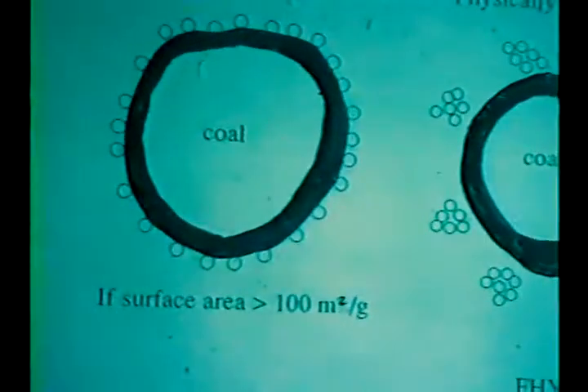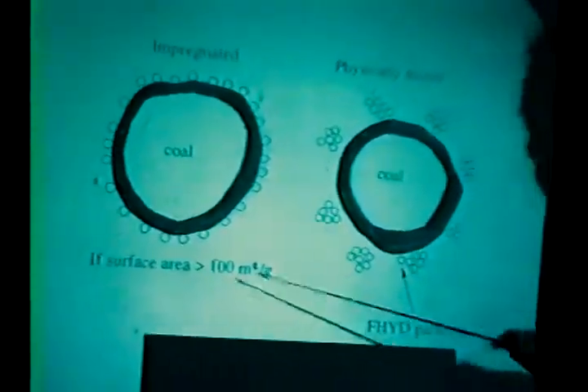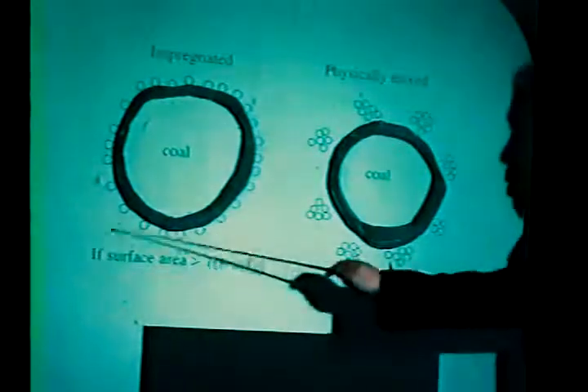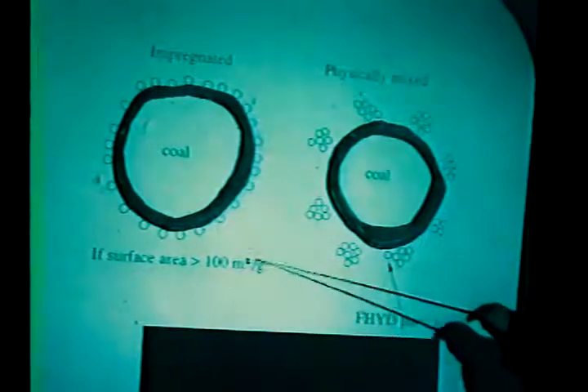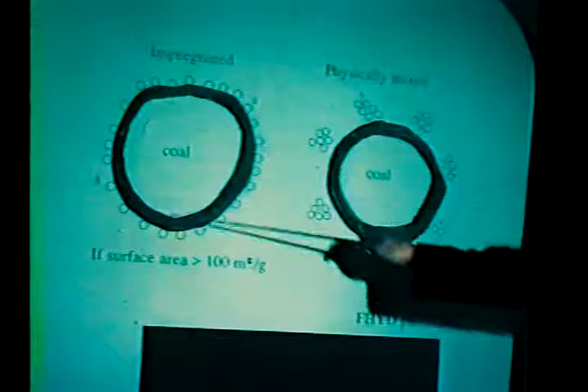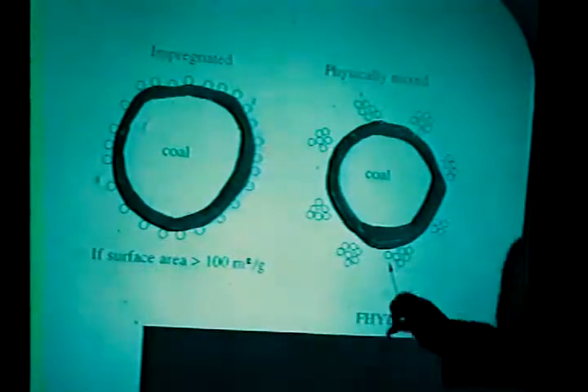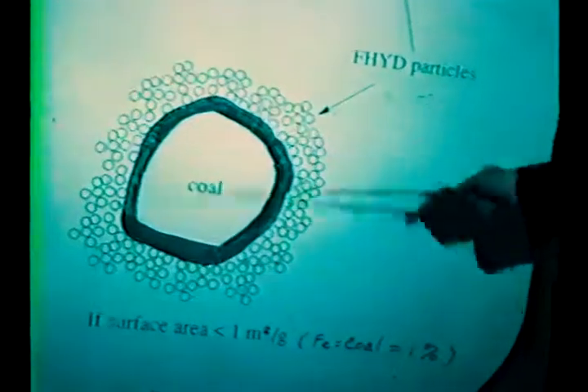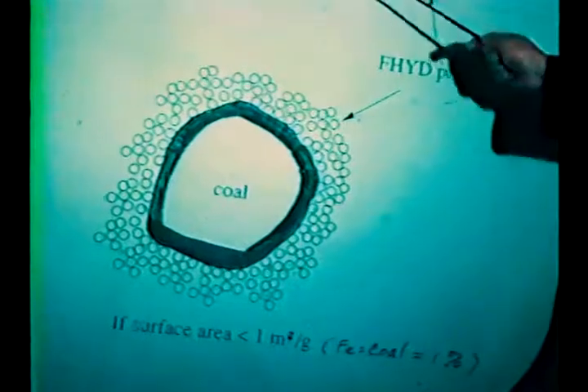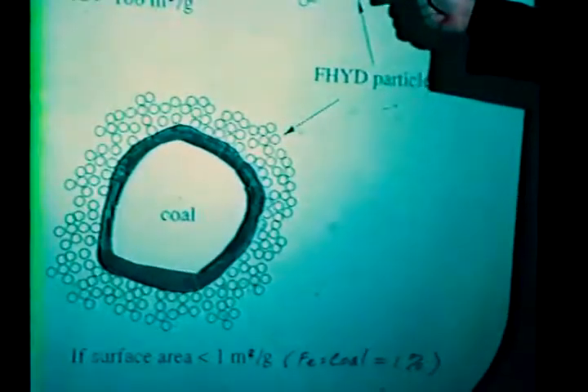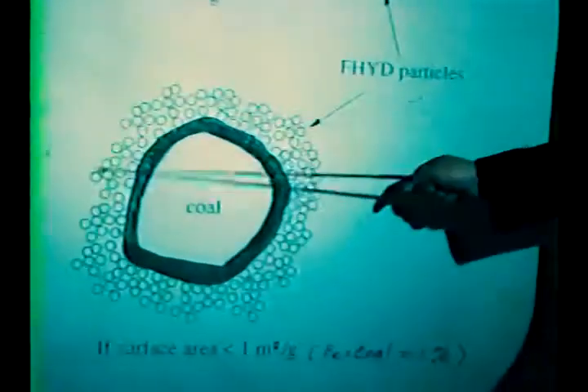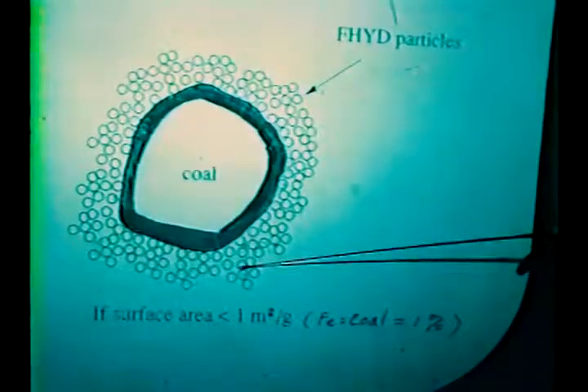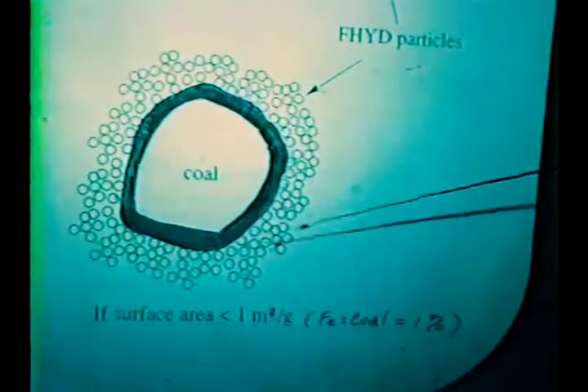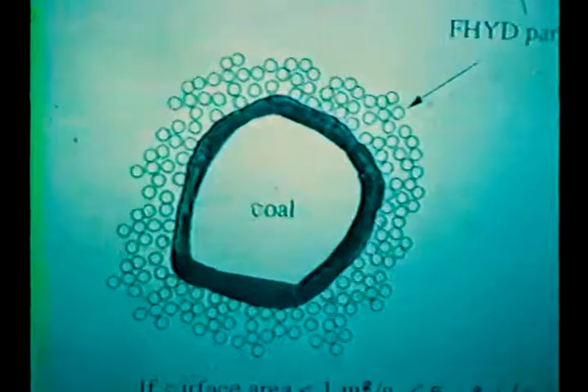But here's the catch. Why? Don't forget the surface area of coal. If coal has 100 square meters per gram, probably you would have this kind of impregnation. But what's the actual surface area of coal? Probably it's only 1 square meter per gram. A simple calculation will show you that you will not have this kind of impregnation. Instead, you will have something like that, because there's no surface area for this kind of impregnation.